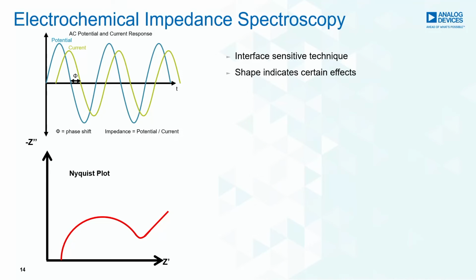A very popular way is the Nyquist plot that you see on the bottom left, where you have the negative imaginary impedance plotted versus the real impedance. And the shape of this Nyquist plot is often very characteristic for certain effects that are happening, and you have a good idea of what your system is doing.